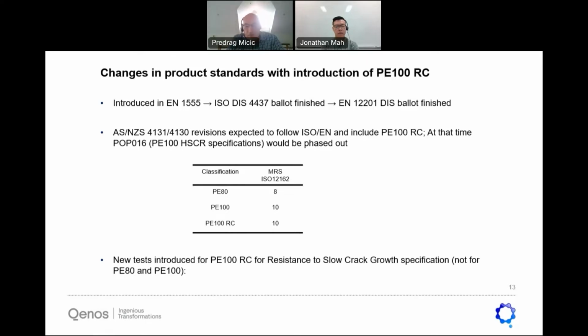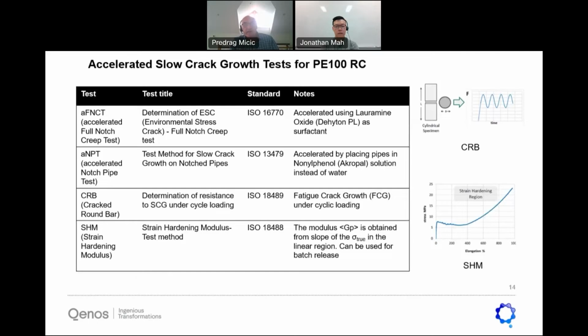So the new tests will also be present there, which are introduced for PE100 RC, and these are the tests that target the slow crack growth specification. They won't be there for PE80 and PE100. This is very specific to the introduction of the new classification PE100 RC. So what are these tests? The accelerated slow crack growth tests for PE100 RC. Actually, there are 4 additional tests that are introduced for PE100 RC compound that were not required previously in product standards for pipe compounds and pipe itself.